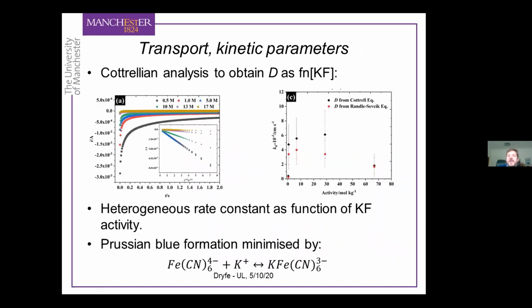And we can do some standard analysis on these CV responses. We can do potential step experiments to extract the diffusion coefficient using a Cottrell type analysis, and you can see the reduction in the diffusion coefficient, from the Cottrell gradient, as we go from the low to the high electrolyte concentration. And we can also extract the apparent standard heterogeneous rate constant for electron transfer from a simple CV analysis, which you can see goes up by an order of magnitude as we increase the concentration of the KF. Though it does fall at the highest electrolyte concentration, the basic message is that the system becomes much more reversible at these high electrolyte concentrations than it is at the low electrolyte concentrations.